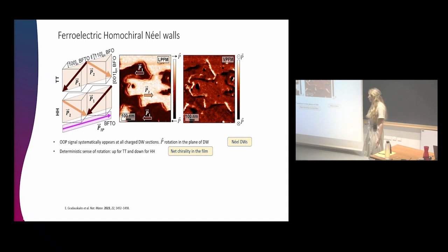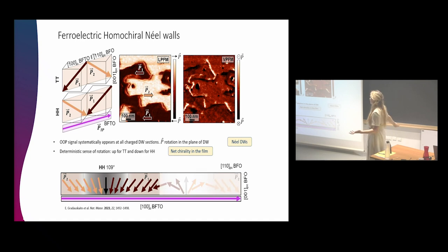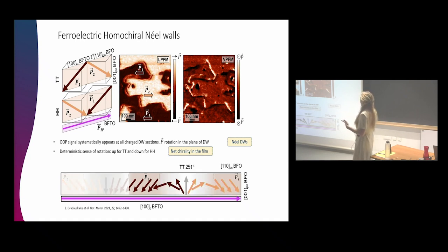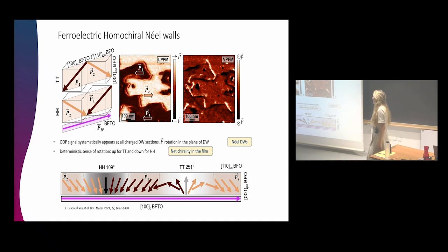So if we now look just at the head-to-head domain wall, here our polarization is going through the downwards polarization. It's already surprising that there's some rotation because ferroelectric domain walls, unlike ferromagnetic ones, are deemed to be non-Ising, so we don't usually expect any polarization rotation just vanishing at the wall. So that's already surprising. But if you look at the tail-to-tail wall, it's even more shocking because now it seems that our polarization wants to really do this 251-degree detour and go through the up polarization consistently at every wall, suggesting that there is some clear frustration in the system that forces this unusual chirality, or so-called homochirality, in the Néel walls.